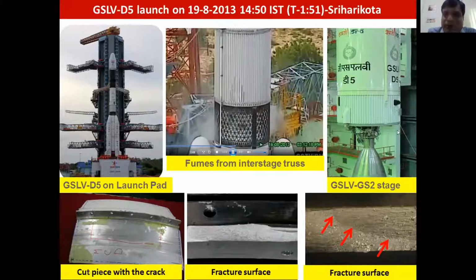So it was dismantled and brought down, and this propellant is very carcinogenic. People waited for 1 week for the levels to neutralize. Subsequently the stage was brought to Mahendragiri. Then we were involved in the full failure analysis of this propellant tank, and in the bottom right hand picture you can see a pre-existing crack on the fracture surface of the propellant tank from the aft end ring. We cut specimens from the location of failure, and there was a pre-existing crack, and this particular propellant tank had been proof pressure tested. That means a proof pressure test is valid as long as you protect the hardware without any further deterioration. Unfortunately, it was stored without proper protection. This pre-existing crack grew at a very odd time during the pre-pressurization before launch.